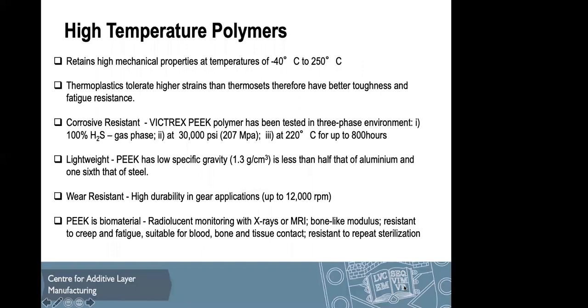For example, they retain their mechanical properties over a wide range of temperatures, from -40 to 250. They tolerate high strains. They are a lot better than thermosets in terms of toughness and fatigue resistance. They are corrosion resistant. So if we talk about a highly corrosive environment, for example, a three-phase environment of 100% hydrogen sulfide gas phase, high pressures and temperatures for a long time, we can discover very little variation in properties on some of the polymers being tested. Victrex have been doing some tests and some interesting studies out there.